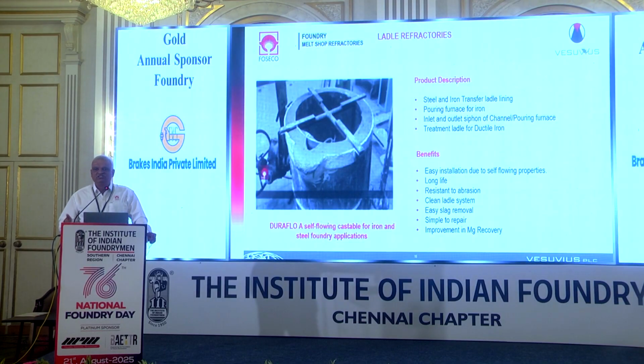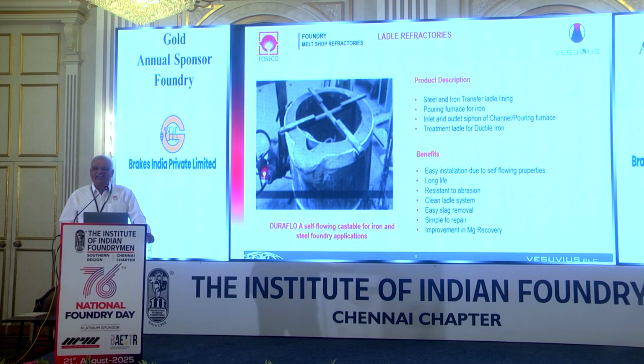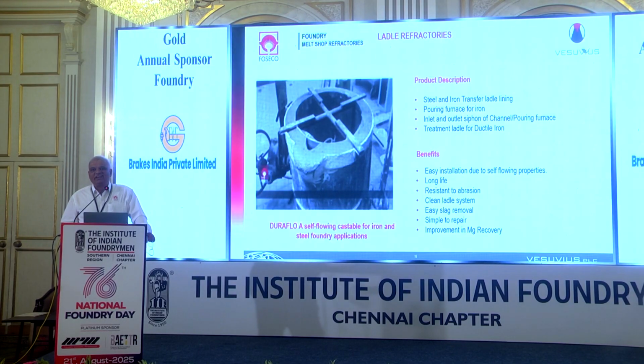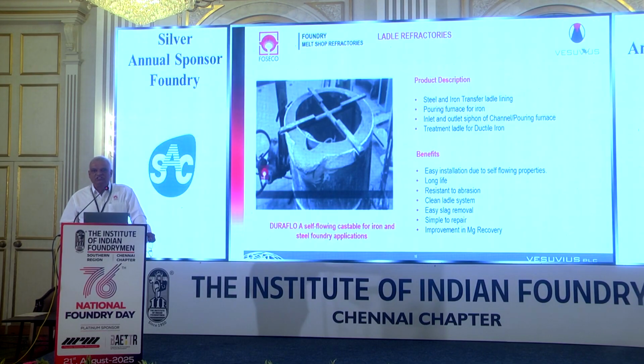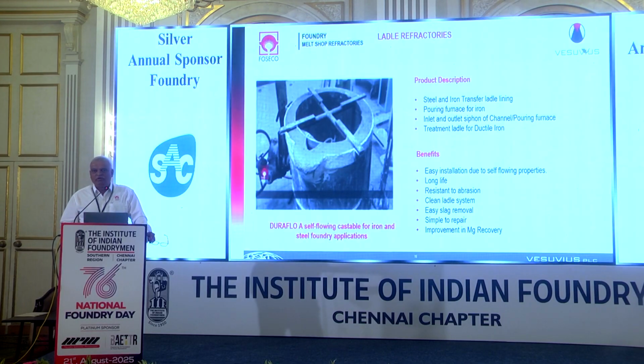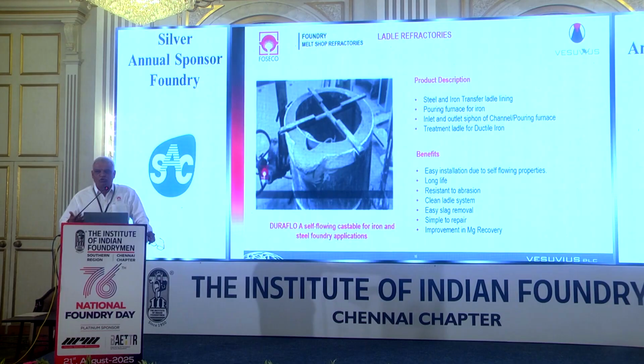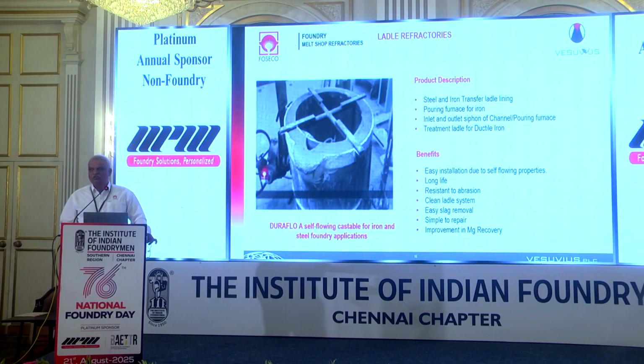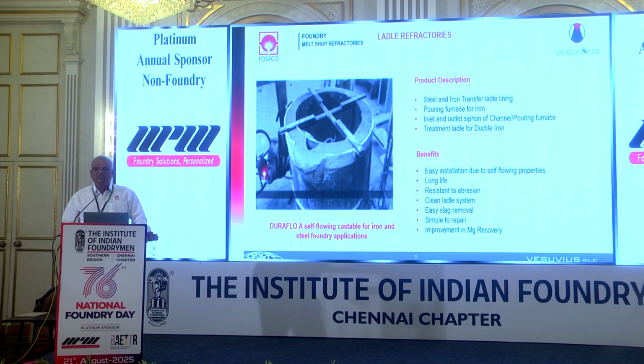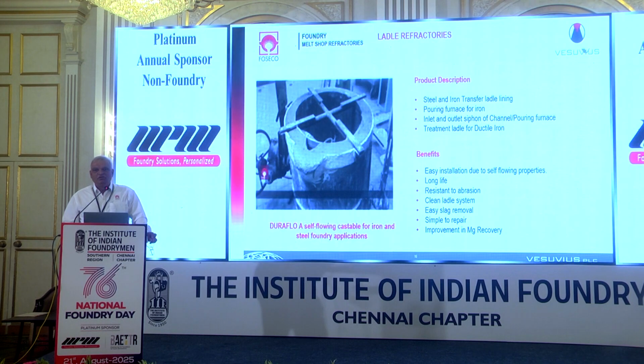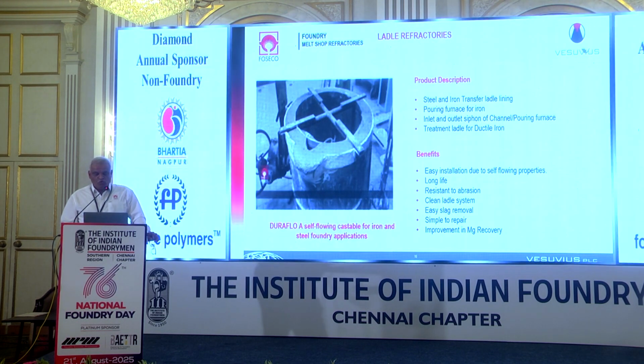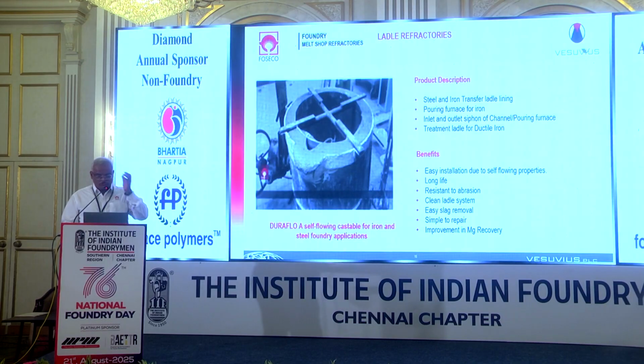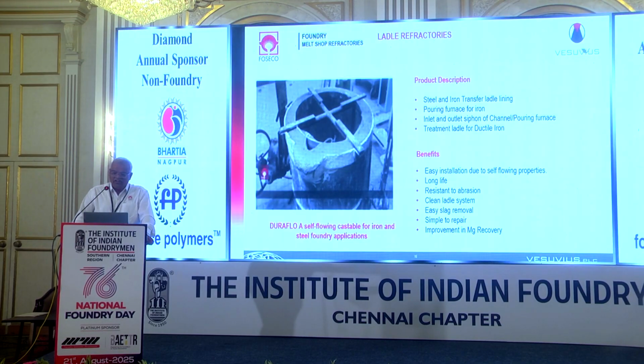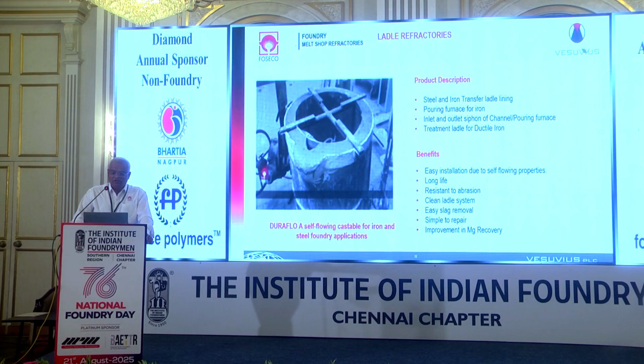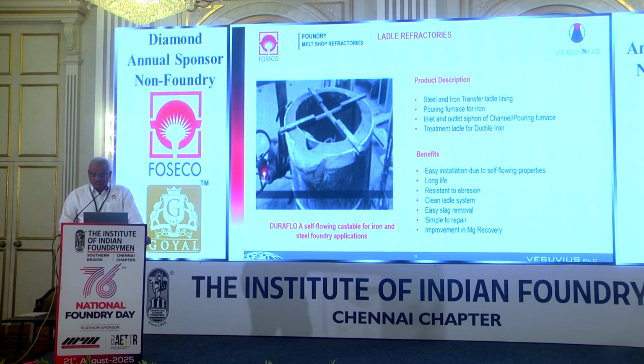As these conventional castables require more water addition, because of the more water addition the material becomes porous and the erosion is faster. To overcome these things, we have developed LC castables, low cement castables also. These LC castables are giving better life and have more stability. They are easy to install, with long life as compared to the conventional castable. Slags are easy to remove.